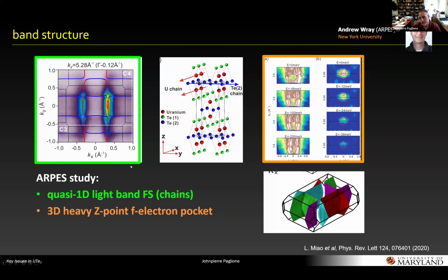And so the question was, where is the F weight? Andrew's group did actually see this so-called Z pocket situated at the top of the Brillouin zone, which seemed to have some F weight to it. And this, they claimed, was a more 3D type pocket. And so goes the controversy. So at least in the beginning, when we did our transport and anisotropy study, we seemed to be able to understand it in the context of a sort of 2-band model, giving a 3-dimensional component of conductivity plus a 2-dimensional component that seemed to make sense.